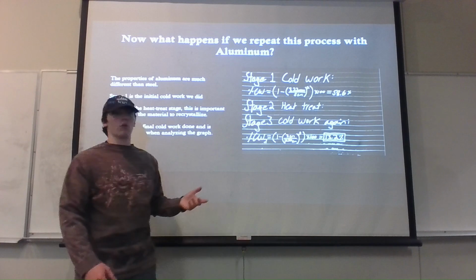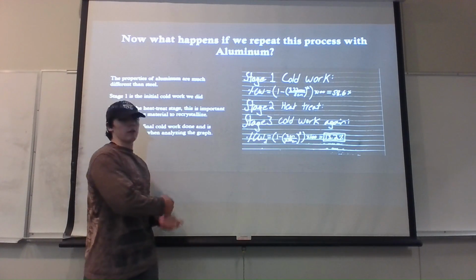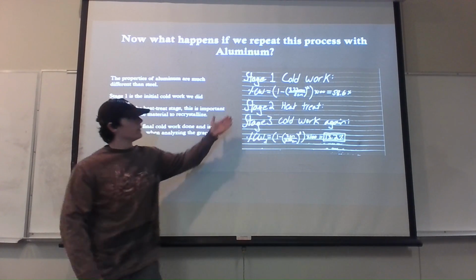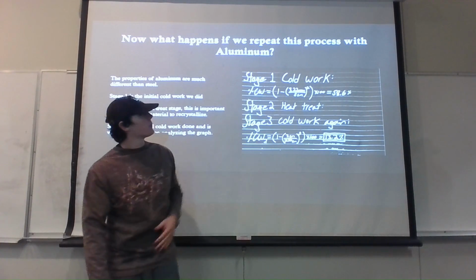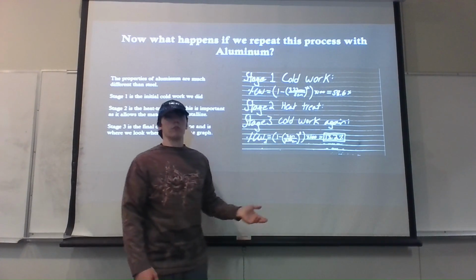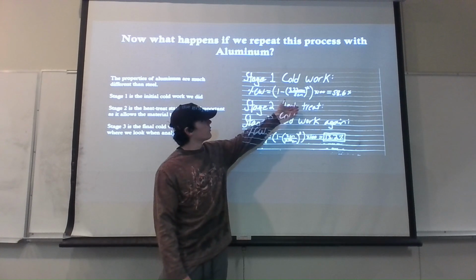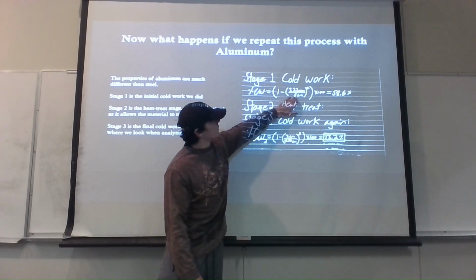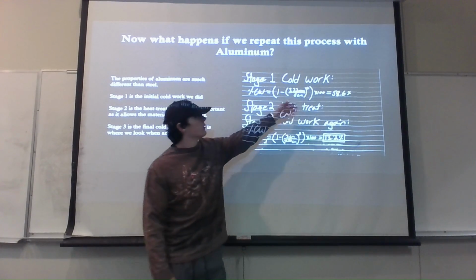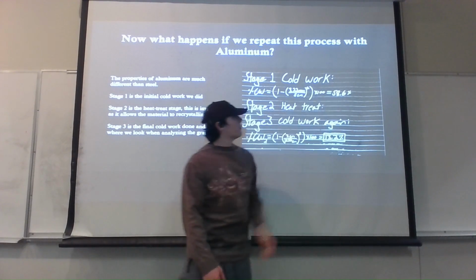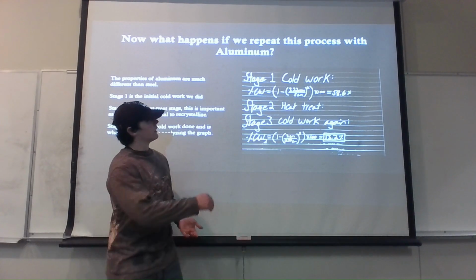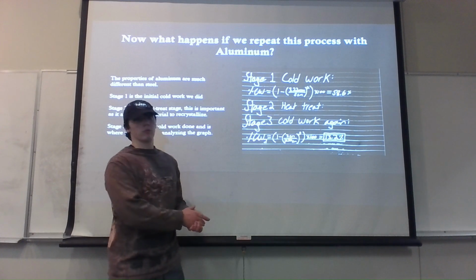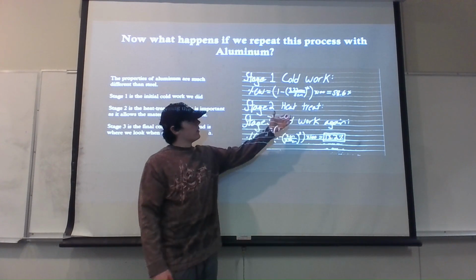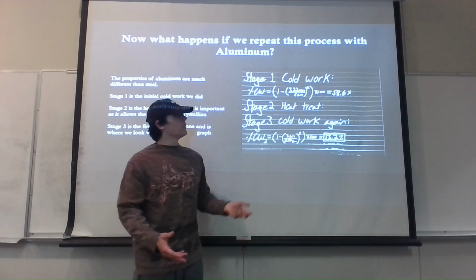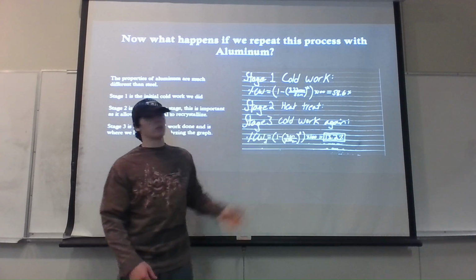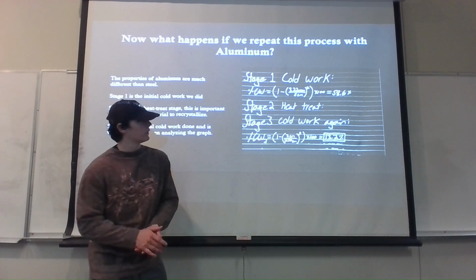So stage 1 is our initial cold work that we're doing. We're getting it from 5 to this 3.22 value, and that's going to be this first cold work that we're doing. So if you plug in the formulas that he was just using before, and then you can multiply it by 100, I think, you can see this is our 5, this is the 3.22, this is the intermediate, and it's 58.6% cold work done to get it from 5 to 3.22, which is where we want it. And then once it's here, we need to anneal and to heal. If we just tried to pull out the whole 64%, it would break, same as with steel.